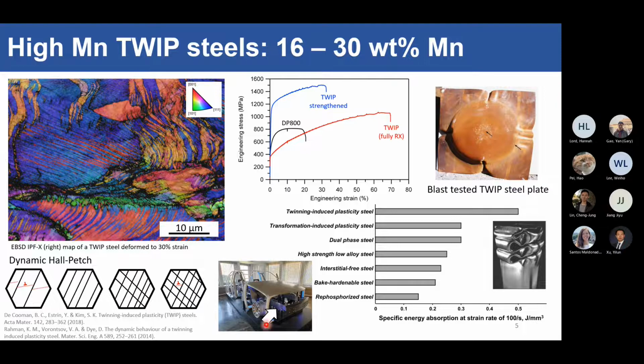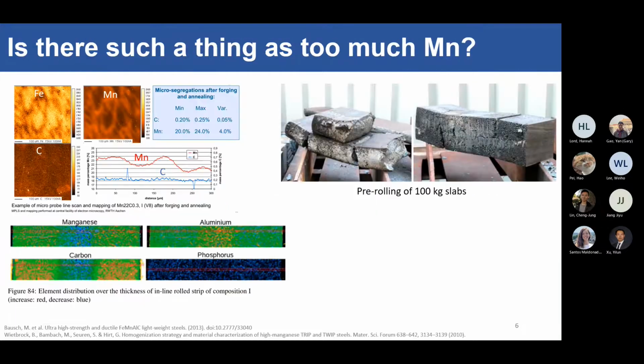So this is a plate of TWIP steel made by Tata Steel. And a few years ago, Dave and Mazan went to go blow it up. And you can see that the TWIP steel actually was very capable in absorbing that blast without cracking. Right, so if TWIP steels are so awesome, how come we don't see them everywhere? And that's because TWIP steels are incredibly hard to cast and fabricate. So this is a very high alloy steels, right?